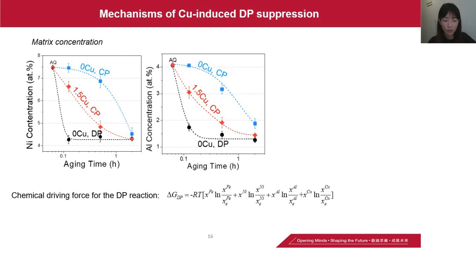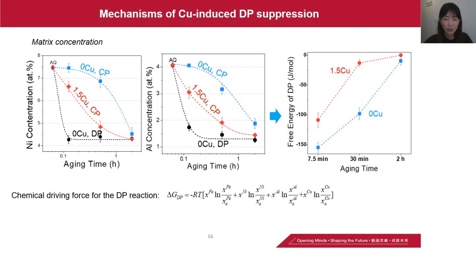the zero copper steel and that of the 1.5 copper steel. The CP reaction of the 1.5 copper steel consumes the supersaturated matrix more rapidly than that of the zero copper steel, which leads to a considerable decrease in nickel and aluminum supersaturation in the early stages of precipitation. Then we calculated the chemical driving force of the DP reaction via this equation. We found that the chemical driving force of the DP reaction is dramatically decreased by copper.